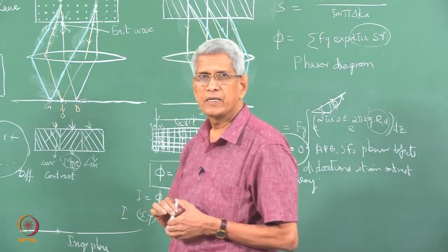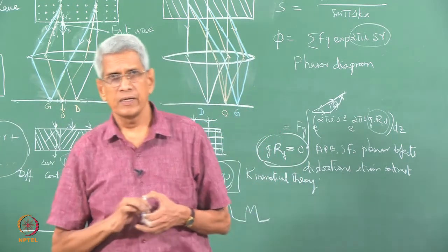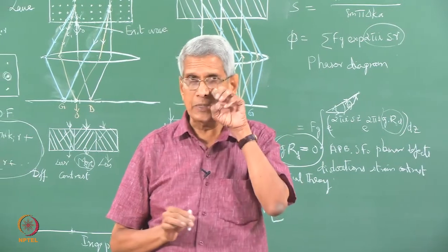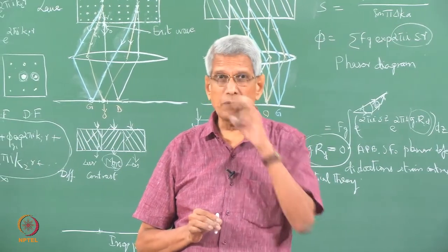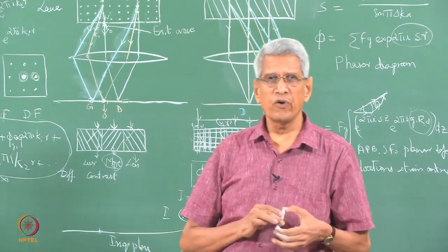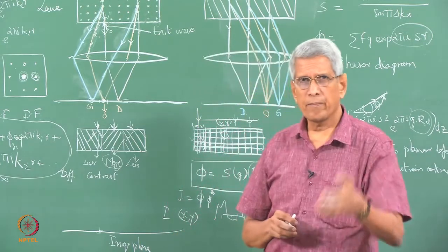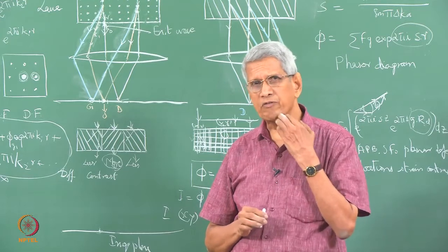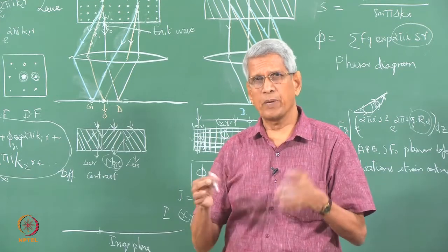This aberration can be minimized, but cannot be totally eliminated in a conventional transmission electron microscope. But what has been seen is that defocus produces some phase error that compensates for the spherical aberration for some particular angles.